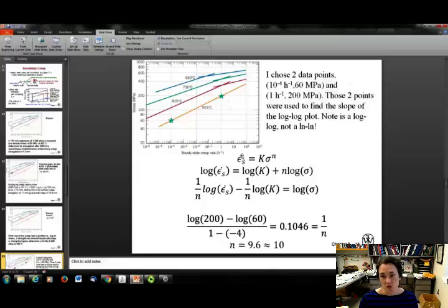Now, if you look at what the log-log plot would be, if I take the log of both sides of this equation, I get log of my creep rate equals log of k plus n log sigma. And then what's plotted here, though, is the stress on the y-axis, okay? So my slope then would not be n, it would be 1 over n. I rearranged my equation here to show that. So I have 1 over n log of my creep rate minus 1 over n log of k. This just becomes my intercept, so it's unimportant to me for my slope calculation. And then that's equal to the log of sigma, okay?